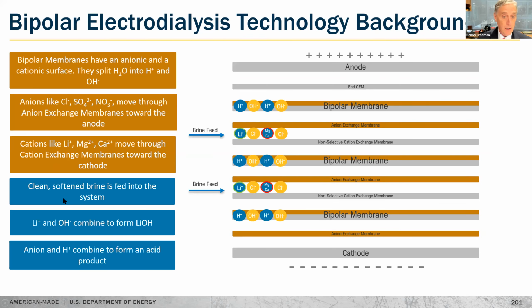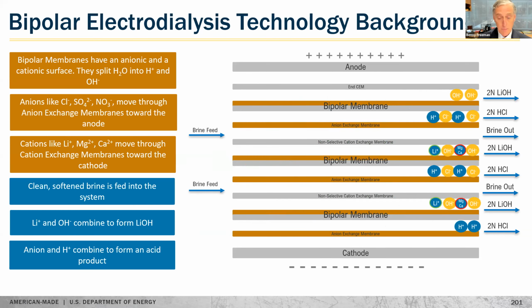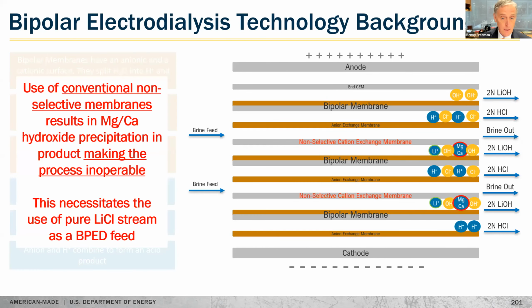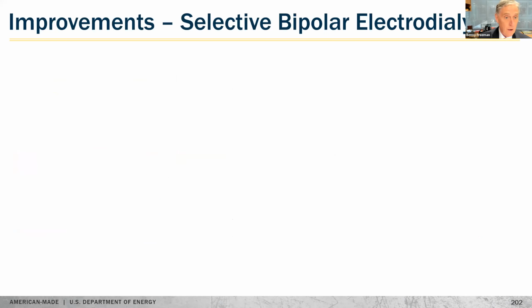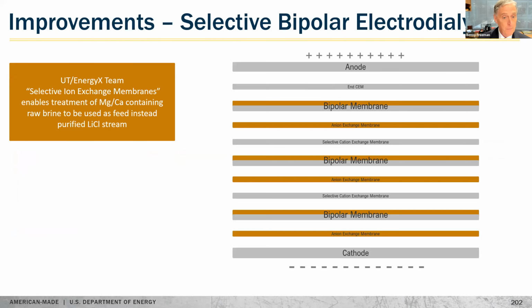And so as we feed brine into a traditional bipolar electrodialysis setup, we make hydroxide at the bipolar membrane. Lithium moves in contact with that to make the lithium hydroxide. The problem is the magnesium and calcium also move with it. And so if you're going to use this process, you have to have ultra clean, ultra softened brine, which is very expensive. And the reason for this is that the cation exchange membranes that are conventionally used are non-selective. Our innovation in this space is to develop a selective cation exchange membrane.